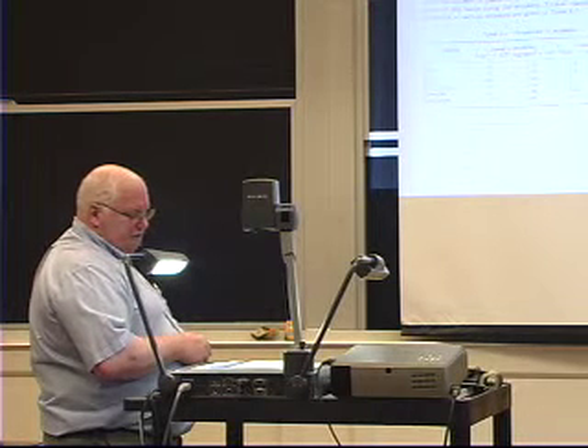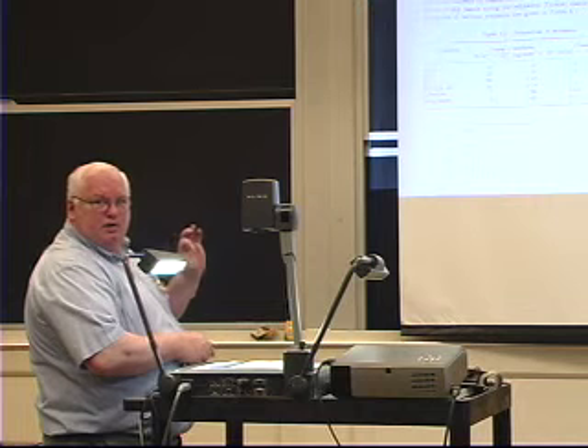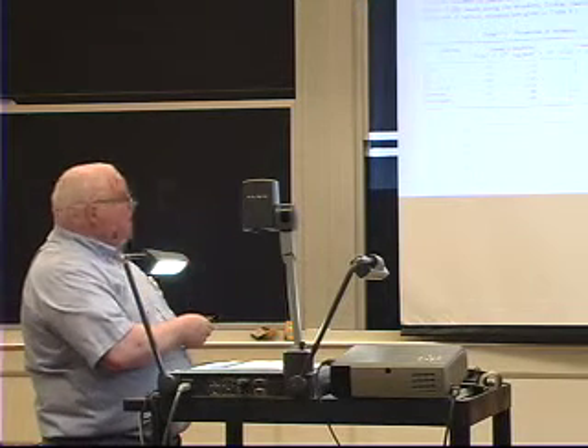A spinel, or not spinel, what's a single crystal aluminum oxide? It's not a spinel, but it's a sapphire. Sapphire single crystal has a strength that has been measured experimentally as 2.2 million psi. These are experimental measurements, okay? Iron, 1.8. Well, I calculated 1.88. Pretty good, huh? Fortuitous, but anyway. Silicon carbide, 3 million psi.